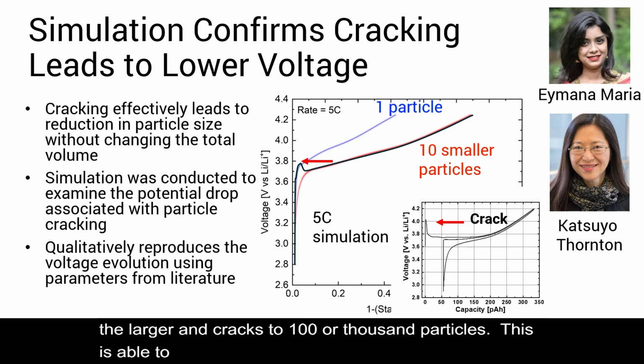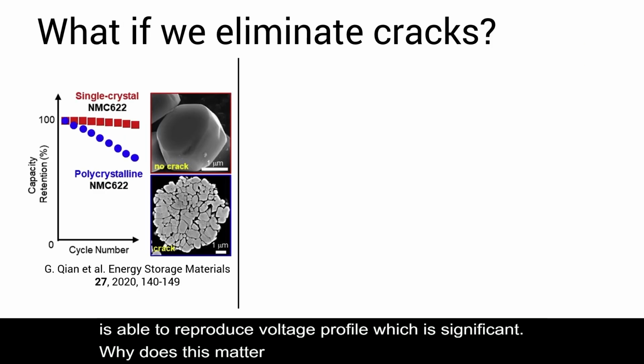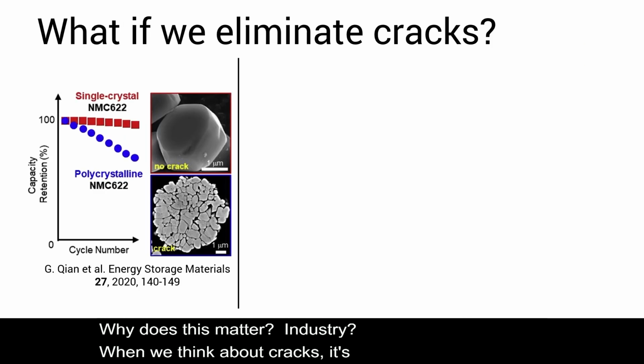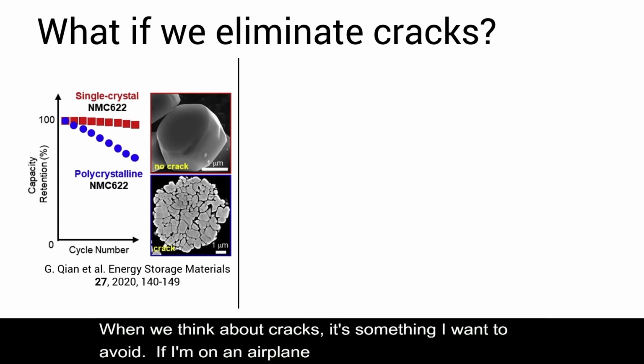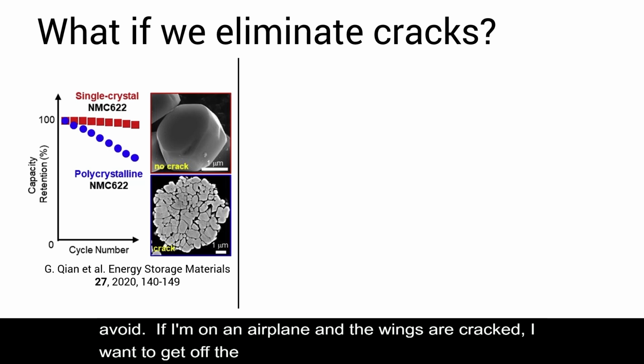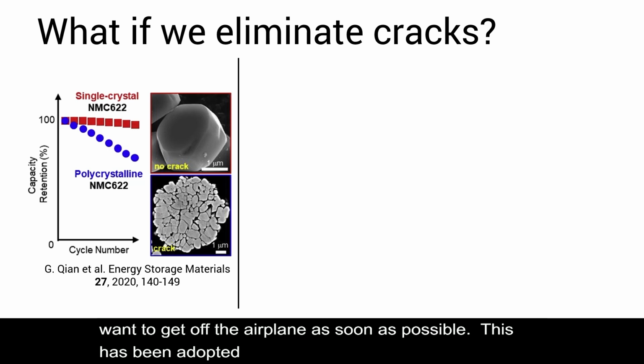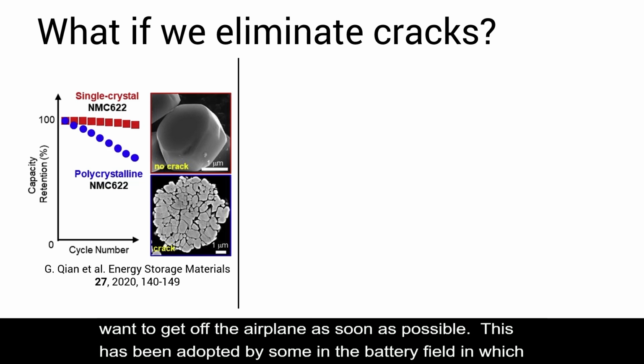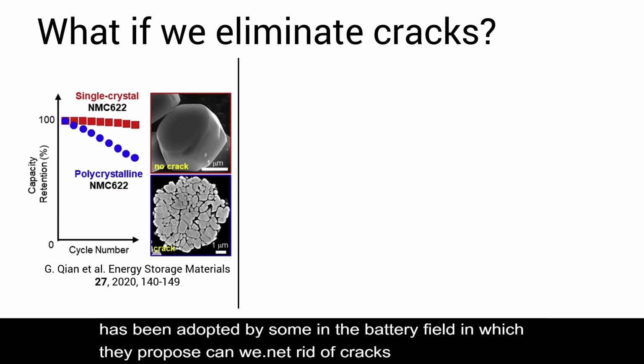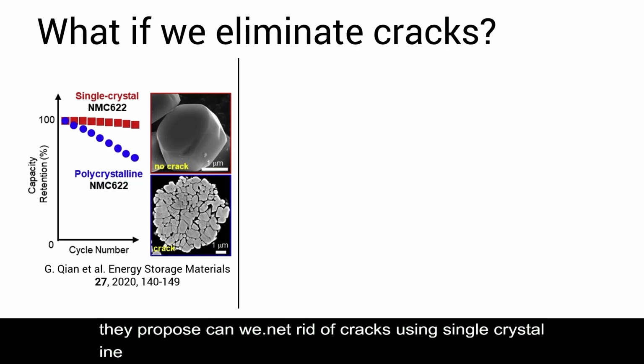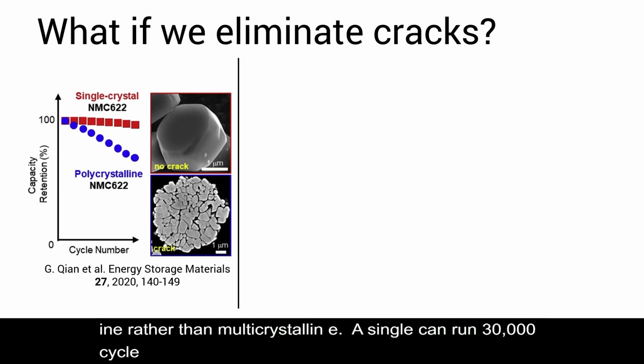So why does this matter for industry? Normally when we think about cracks, it's something that we want to avoid. If I'm on an airplane and I see the wings are cracked, I probably want to get off the airplane as soon as possible. So this heuristic has been adopted by some in the battery field, in which they propose, can we get rid of cracks by using these single crystalline materials rather than this agglomerate of polycrystalline where they sort of run into each other. And the proposal is that a single crystal can have much longer cycle life. Some people say that a single crystal can run 20,000 cycles, or 30,000 cycles, which is equivalent to a car that's able to go 1 million miles before degrading.